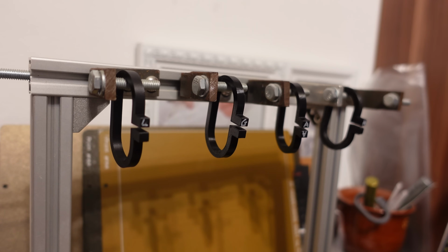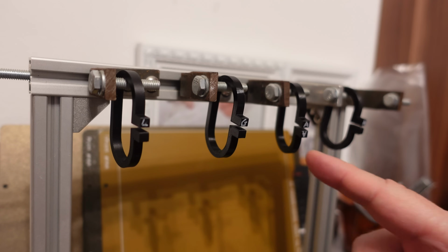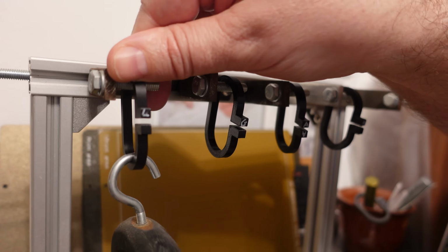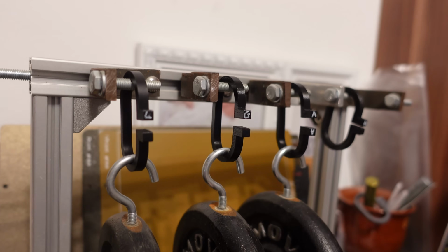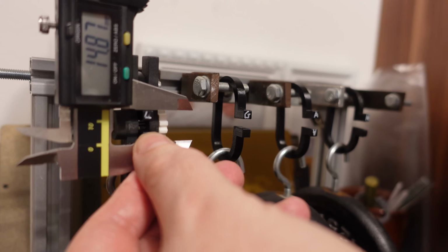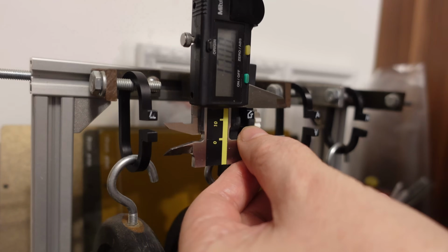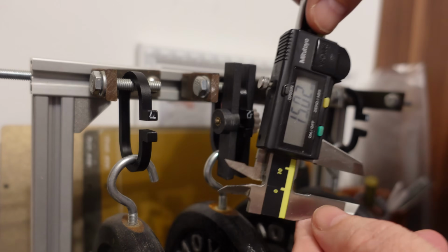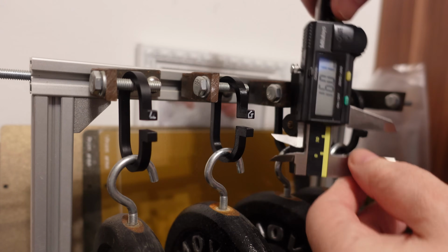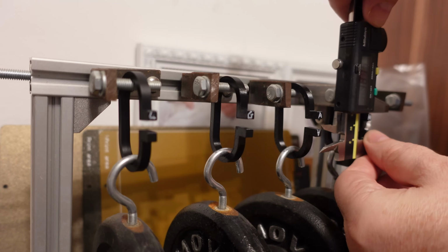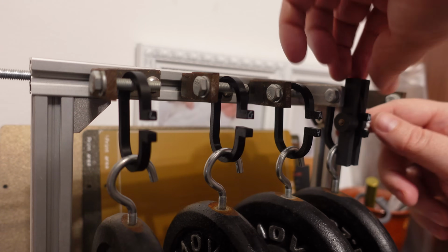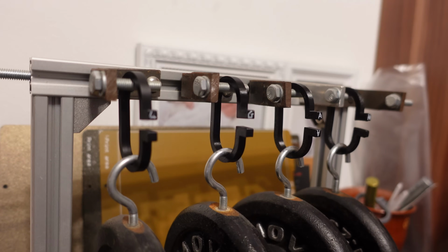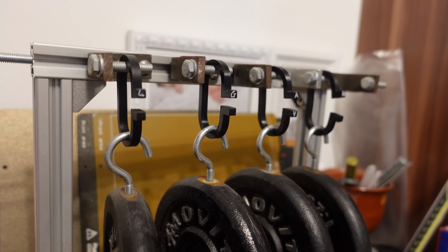Creep as a deformation under constant load: PLA, PETG, ABS and nylon. 14.87, 15.02, 16.01, 18.14. This is day 5, very typical behavior from some materials like from this nylon, but let's measure them and then we will analyze the numbers.